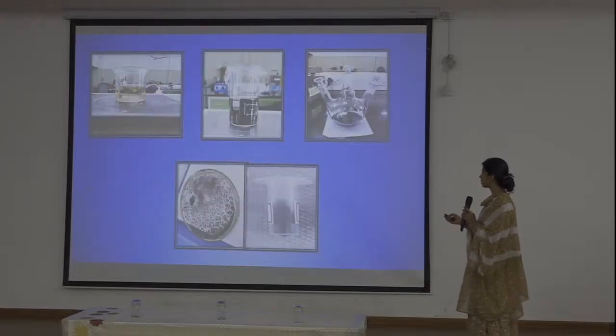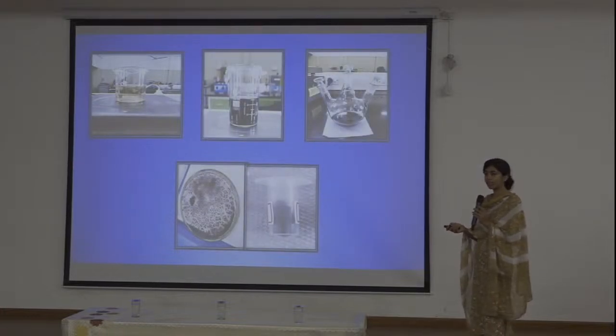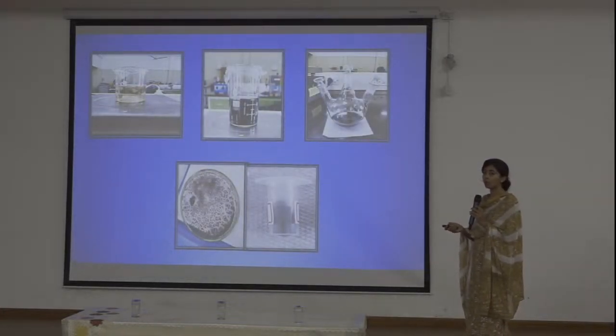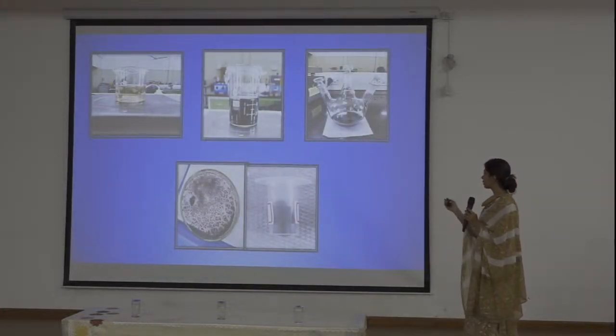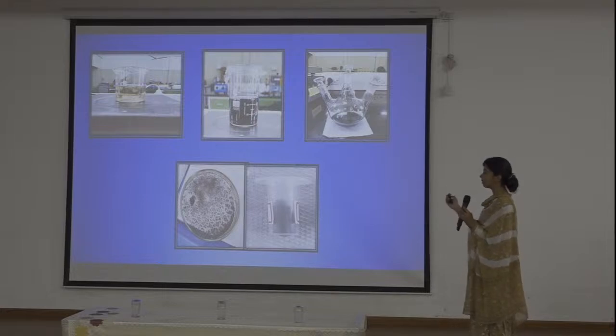For the preparation of the nanocomposite, after this homogeneous solution, we need to add 0.2 gram of activated carbon, and do the same process: 420 watt of microwave radiation for 15 minutes at 160 degrees Celsius. So this is the method.